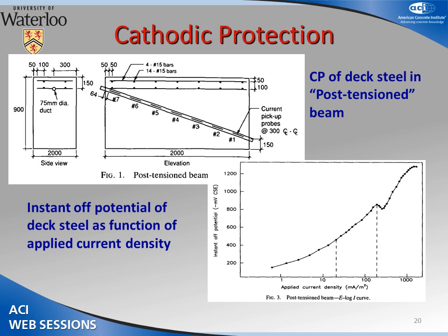And this was the plot of instant off potential. It's written as a negative, so this is minus 1,000, minus 800, versus the applied current density. And this is the area here, about 1,100, with a more negative voltage than this, hydrogen is evolved. So he was recommending to the Ministry of Transportation and other authorities that the current density that should be applied is this approximately linear region here.